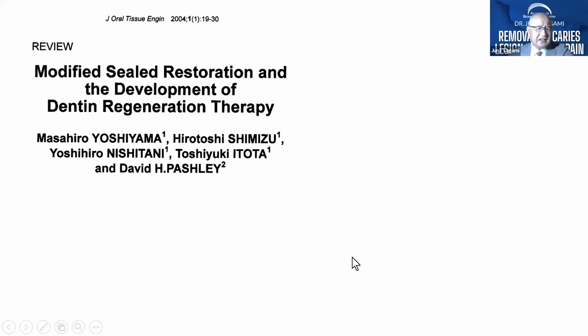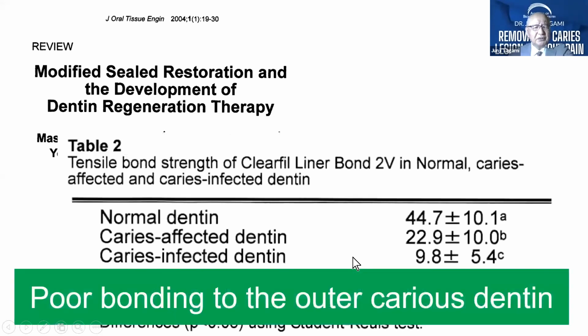And in this study, the bonding to the outer region was evaluated. The bonding is extremely low because the dentin structure itself is very, very weak. It's not a good substrate for bonding.